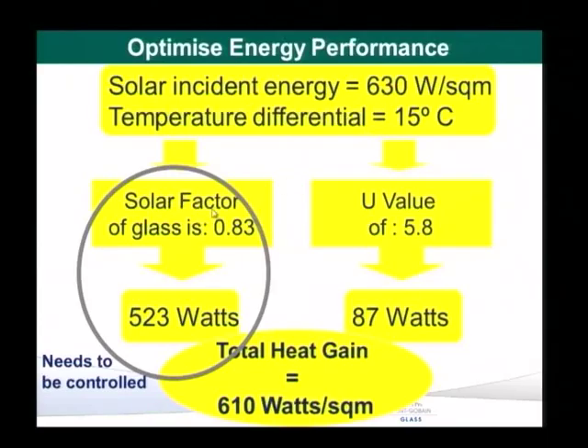Say we used an even lower solar factor of 0.2. The total heat coming through the glass would be further reduced to 126 watts and the total heat gain would be much lesser, at approximately 200 watts per square meter. So it's easier to control the performance in a tropical country by controlling the solar factor of the glass.